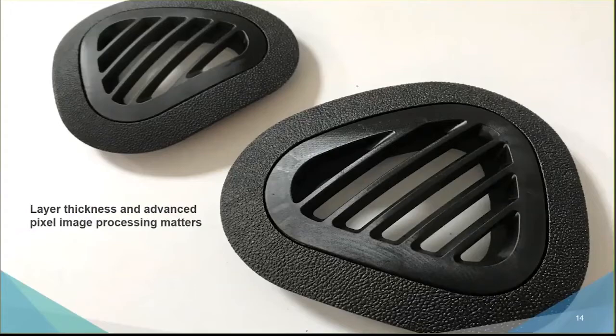The other interesting thing about Figure 4 is the ultra-high fidelity — very, very thin layers. Relative to stereolithography, there's an order of magnitude thinner: 10, 20, 30 micron thin layers combined with microscopic blended 65-micron pixels. Using gray scales and advanced imaging techniques, this enables smooth production-grade sidewalls on demand as well as production-grade digital textures. For production, if you have to sand parts — even one minute per part times 5,000 parts — it's impossible to scale.